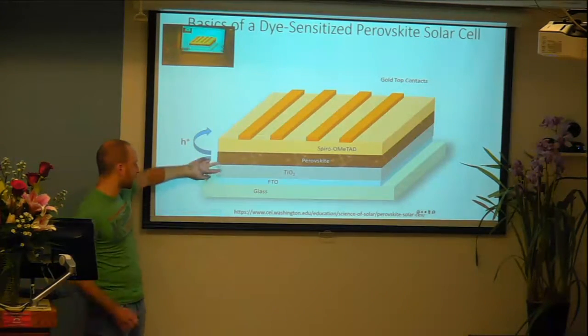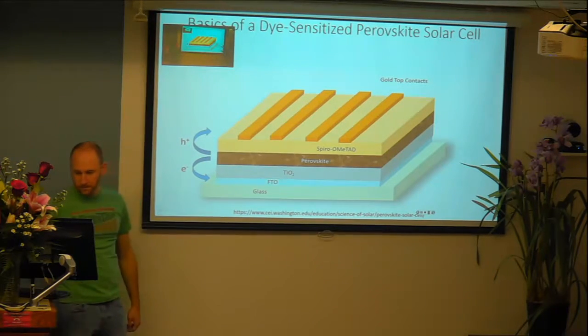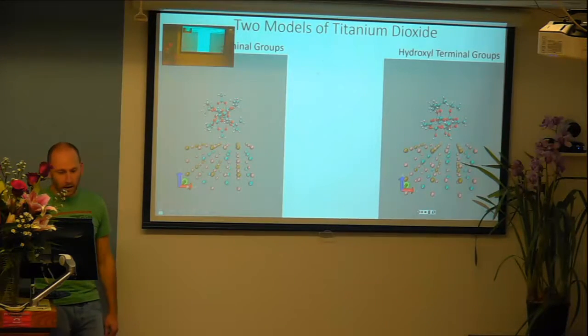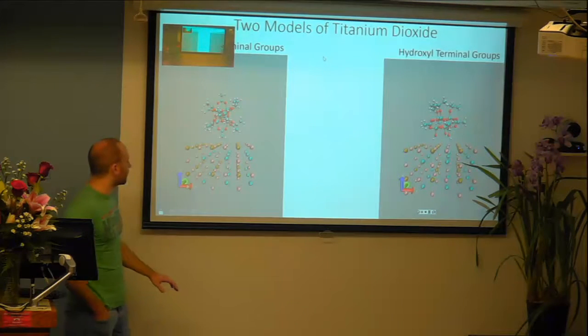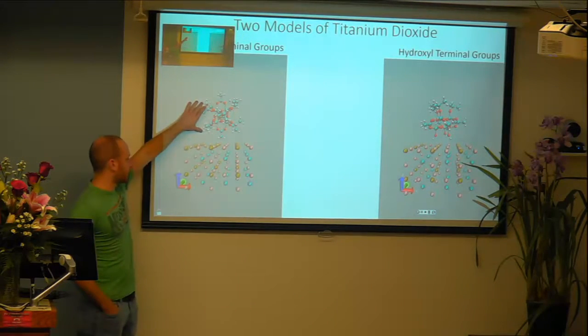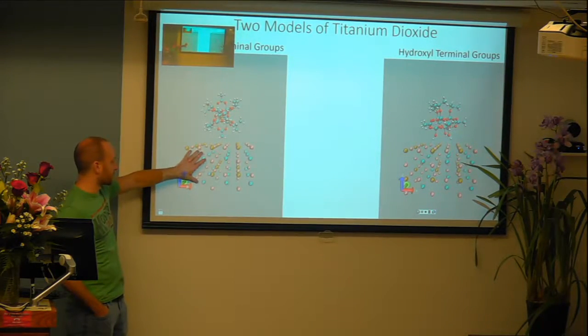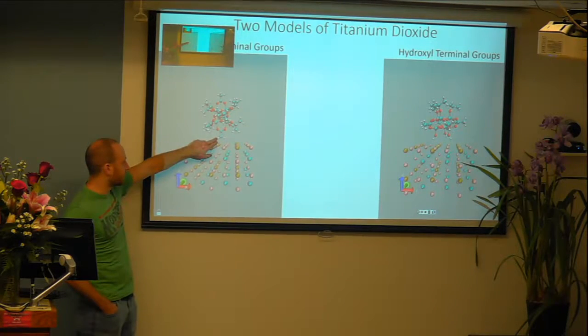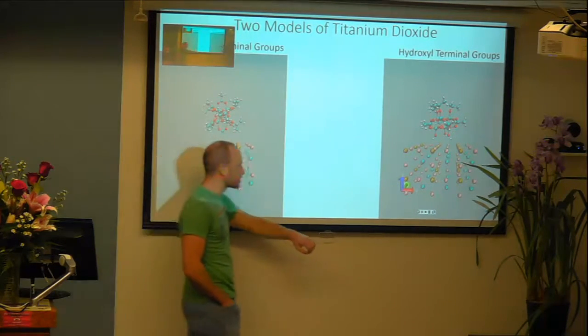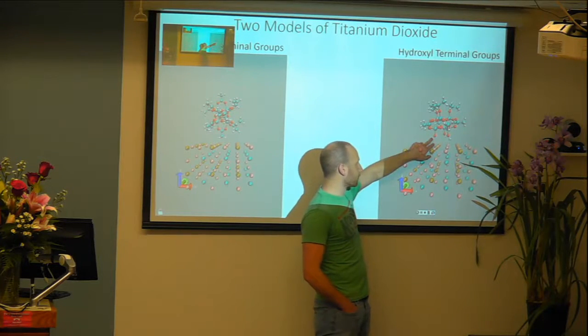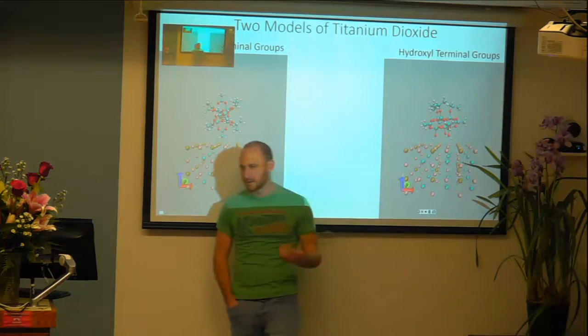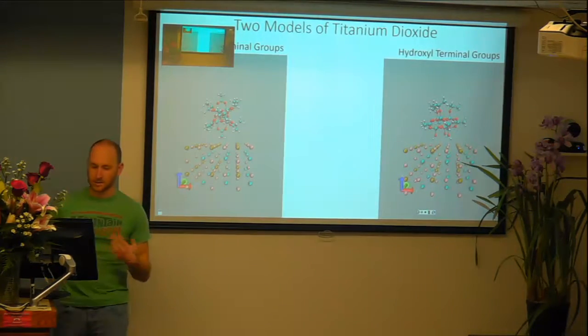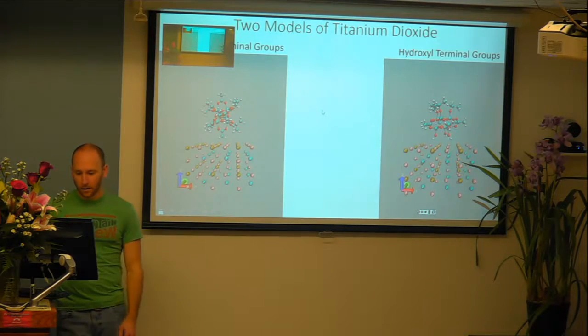So in particular, I'm looking at this interface here. These are the two models that I'm working with. We've got the titanium dioxide on the top and the perovskite on the bottom. We have an isopropanol linker group in this case, and we have hydroxyl linker groups in this case. We're just looking at the differences between these and trying to characterize them generally.